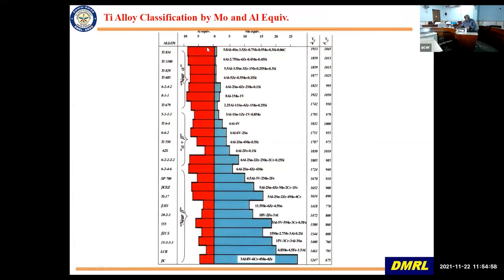And you can see you have higher aluminium equivalent and a very small amount of beta stabilization in the near alpha alloys. And then as you go down, the amount of alpha stabilization decreases and beta stabilization increases. The other thing is that the beta transus temperatures are indicated here for several commercial alloys. You can see as you come down from near alpha alloys to beta alloys, the beta transus temperature is also roughly going down.